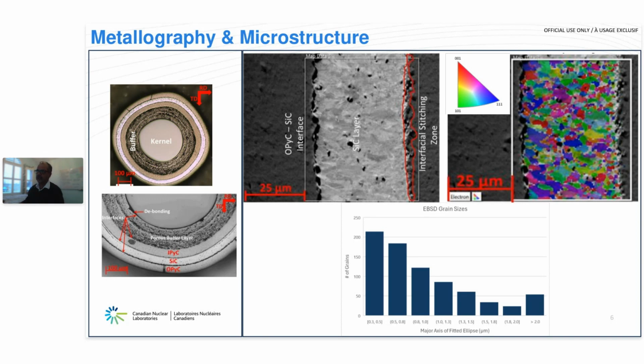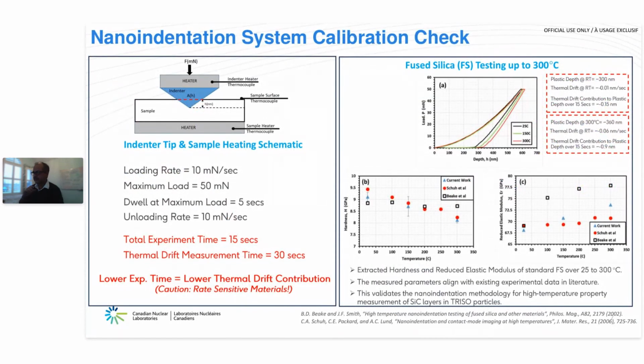So we prepared the sample. We looked at the metallography and the microstructure of the material itself, and now it's time to start testing the sample. And as Professor Janet very articulately described the importance of calibration of the system before testing, I must admit that we adopt a similar methodology, starting with load calibrations, depth calibrations when needed, and the diamond tip area function, which is characterized on a routine basis before and after testing in our lab. But we do this only at room temperature. We do not do the calibration checks at high temperatures, but that's something we would like to adopt going forward as continuous improvement.